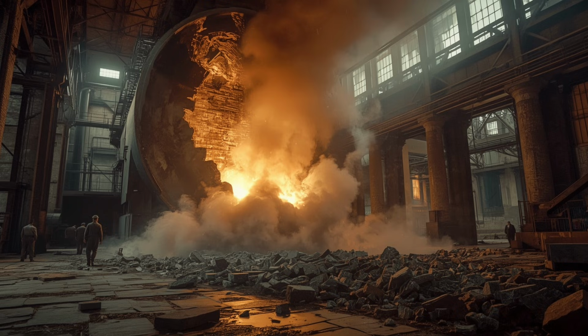The number 3 atmospheric condenser, a sealed iron cylinder 12 feet tall and 6 feet in diameter, had ceased to exist as a coherent object. But the room around it showed none of the expected signs. No scorch marks on the brick walls. No outward blast pattern. The heavy iron door to the chamber hadn't been blown off its hinges. It had been sucked inward, hanging now at an impossible angle, its hinges bent toward the interior.